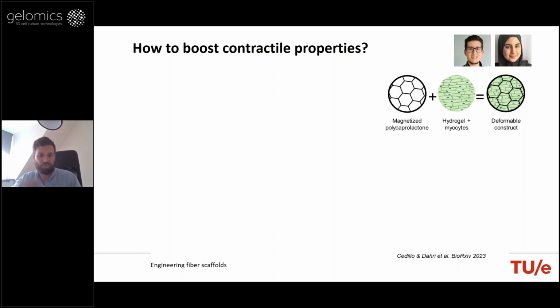What we observed is that for the thickness of the constructs that we have, the contractile force that we generate is not sufficient to replace the contractile force that was lost in the infarcted region. So one aspect was, of course, to scale up the constructs, so make them thicker. But when you make them thicker, one of the challenges is vascularization, because the cells consume high amounts of nutrients and oxygen. So vascularization starts to kick in as a very challenging problem that we have to address.